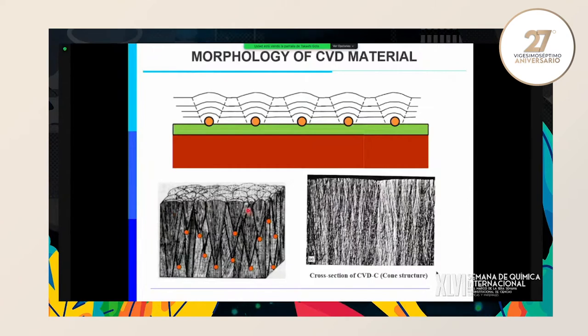We can call this a cone structure, like a cone of ice cream, like this one. Nodule structure or pebble structure, many people say many names. The nanoparticles become a nucleation site one after another. This microstructure also contains impurities. This is a microstructure of CVD carbon, which is a very, very important material in industry. So this also has so many cones here. Soot of carbon in the gas phase becomes a nucleation site of the deposition.